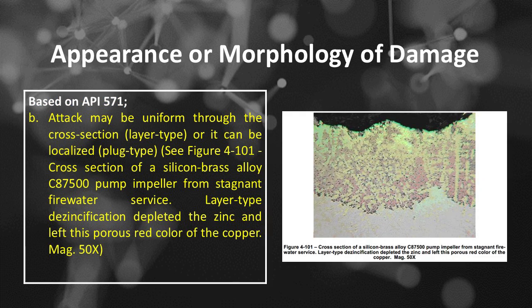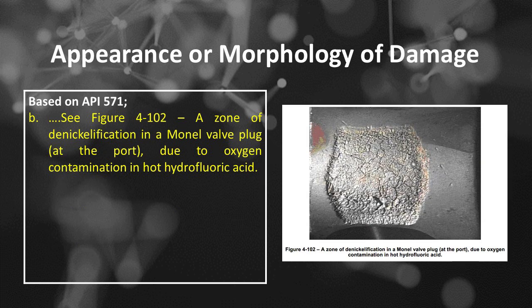Number B. Attack may be uniform through the cross-section, layer type, or it can be localized, plug type. See Figure 4-101, cross-section of a silicon brass alloy C87500 pump impeller from stagnant firewater service. Layer type dezincification depleted the zinc and left this porous red color of the copper. Mag. 50X. See Figure 4-102, a zone of denickelification in a Monel valve plug, at the port, due to oxygen contamination in hot hydrofluoric acid.